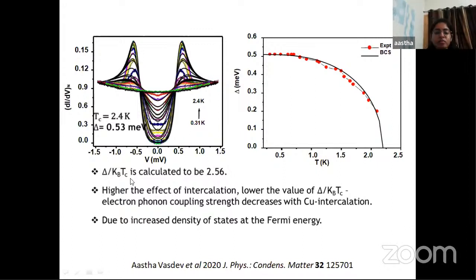Okay. So if we calculate the delta by kBTc for this, it is found to be 2.56, while in the previous case, where the effect of intercalation is lower, it was 3.15. So we can say that the higher the effect of intercalation, the lower the value of delta by kBTc, which tells us the electron-phonon coupling strength. This means the electron-phonon coupling strength decreases with copper intercalation.